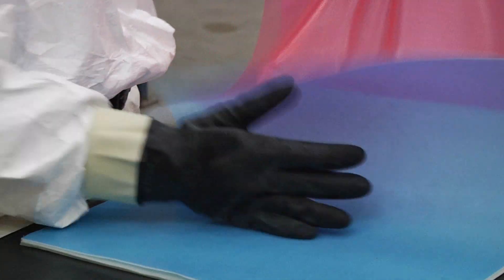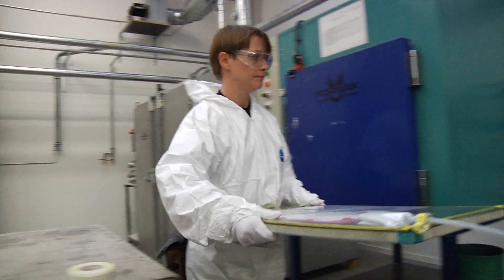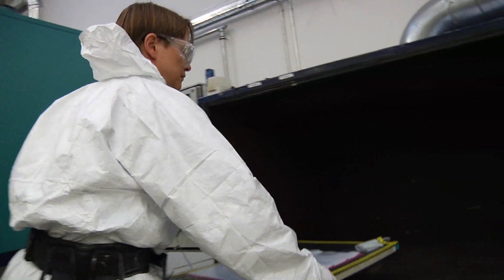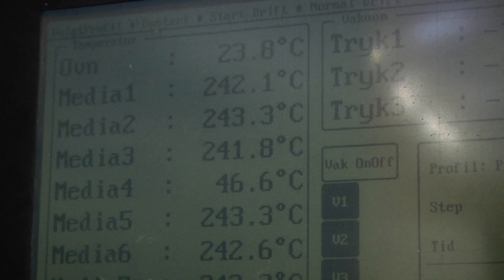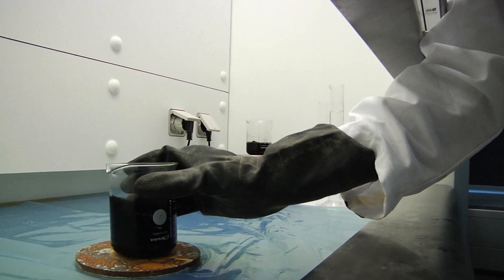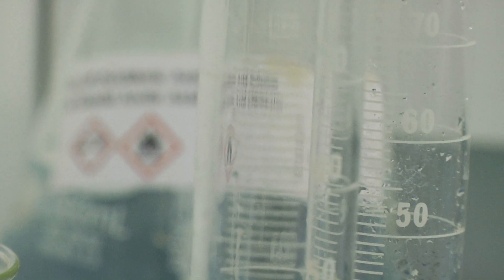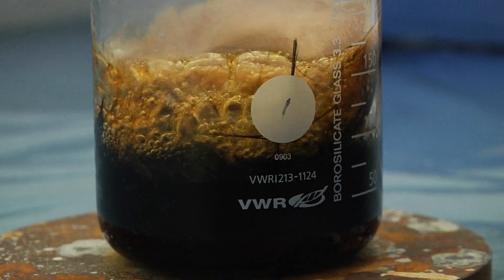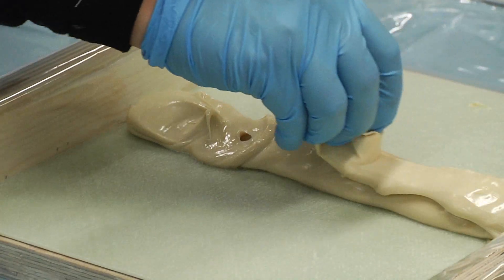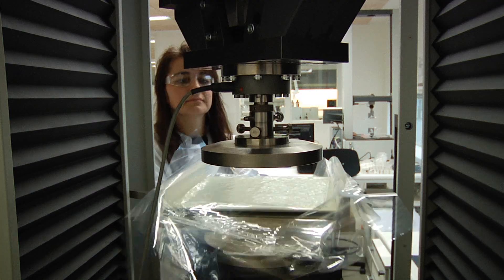The testing starts in a workshop close to the lab where the composite laminate is created in a vacuum to simulate the blade production. Acid is used to remove the resin from the carbon fibre to measure the mass of both individual materials. The strength of the glue is tested using a method to closely simulate the bonding of the individual components which go into the complete blade.